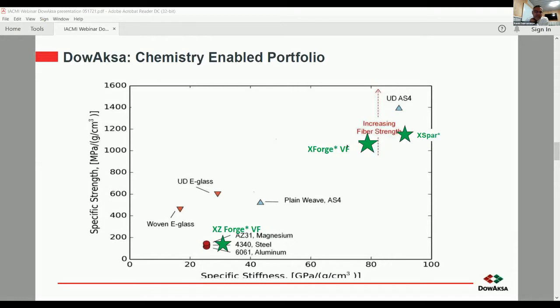So XForge is basically the prepreg made with unidirectional fabric, and the XZ Forge is after you kind of chopped it up and put that into a mat. That gives you some strength in the Z direction also. Of course, you lose some performance compared to the unidirectional fabric, but this has got certain specific advantages in giving you performance in molding and parts that are very difficult to do otherwise.